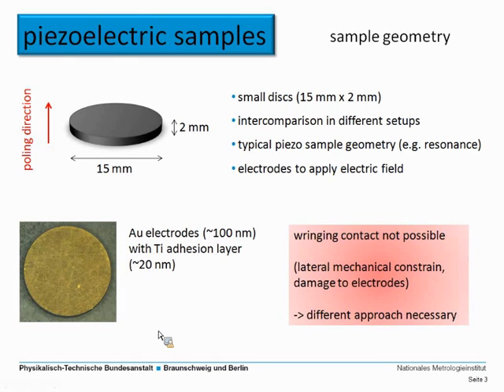This is just a requirement we have for the general sample geometry, but as a drawback, it makes the wringing contact, which Guido mentioned in his talk, impossible. All the other samples are wrung to a reference plate just to measure the length of them relative to that reference plate, and this wringing contact is not possible in this case, because for one, it would damage the electrodes, and it also introduces some kind of mechanical constraint.